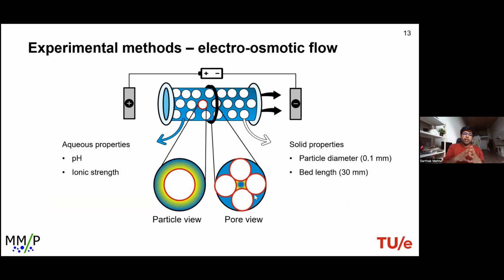Now we understand that because of the pores formed by the silica particles coming together, it is actually the center diffusive region that contributes to the electroosmotic flow. We again use non-porous silica particles of 0.1 mm diameter, and we vary pH and ionic strength.